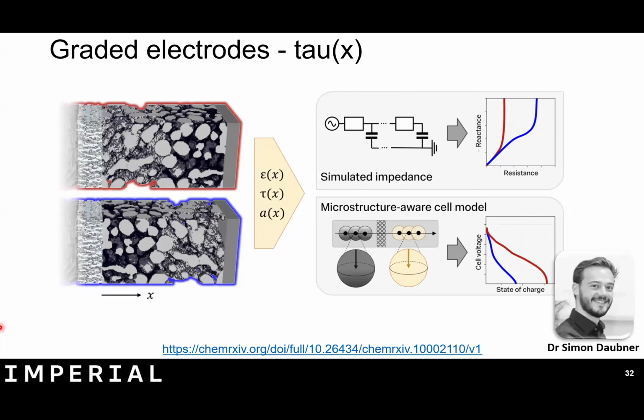So Simon Daubner in my group has recently published a fantastic study around quantifying tortuosity as a function of depth through a sample, which cannot be done by putting tau through little subdomains, because eventually, if your subdomain gets smaller and smaller, tau will tend towards 1 anyway, which is meaningless in this context. So instead, he simulates across the whole domain and then applies a nice closure relation to specify tortuosity as a function of x. And what we've shown is that by having volume fraction, surface area, and tortuosity as a function of x, you can use these to parameterize equivalent circuit models, like transmission line type models or Doyle-Fuller-Newman models, and really accurately reproduce the results of 3D simulations with just these 1D metrics, which is not possible with electrode average tau, epsilon, and A. So it's a really exciting result and really important for next generation cells.